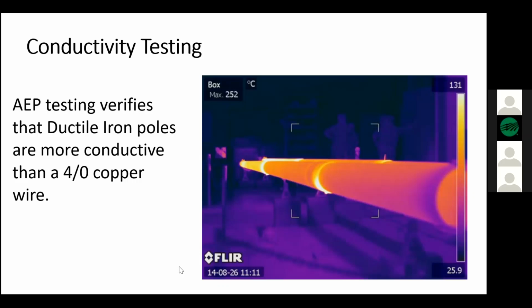We still recommend that you ground the ductile iron pole as you would a wood pole, because our ductile iron poles are considered wood pole equivalent. However you ground those today, we recommend you continue that practice. But in the instance that the grounding or the copper is stolen, you still have the assurance that the pole is still conductive.